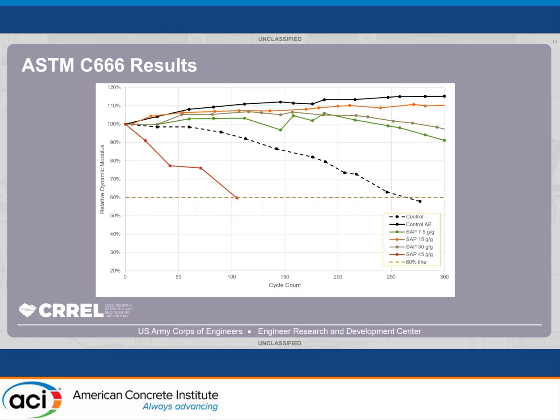As you can see here, our numbers were switched a little bit, but our lowest dosage, which was at 2.25 per yard, failed at just over 100 cycles. Going up to the top, if you can see my mouse, our control that was air entrained stayed here at the top with this black line. You can see it did pretty well with this testing. And our control that did not have any air entrainment failed just before the 300-cycle mark.